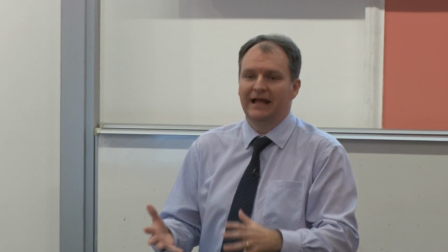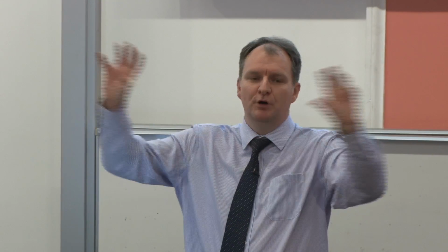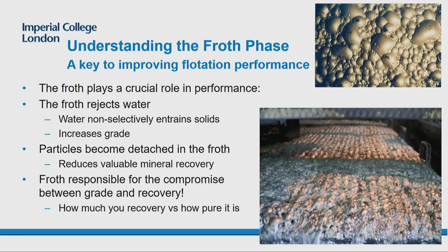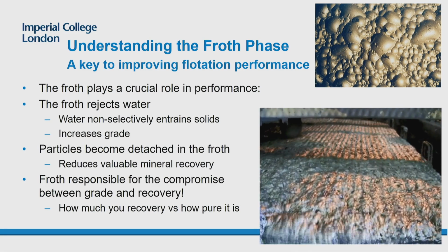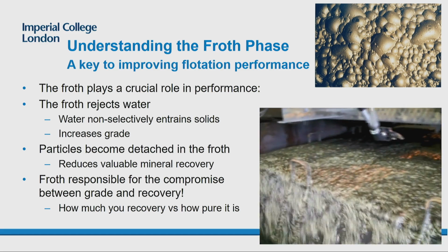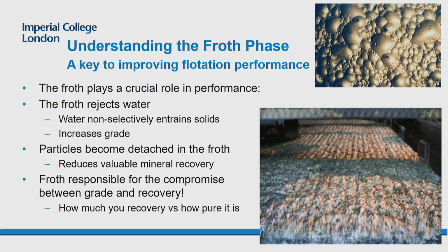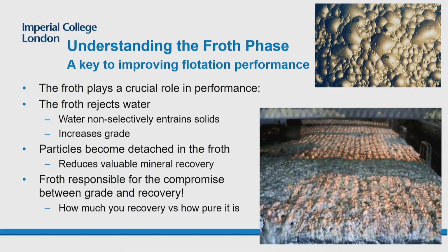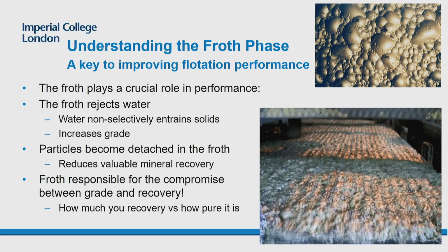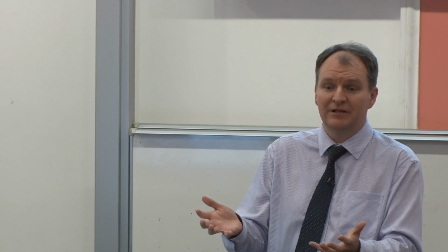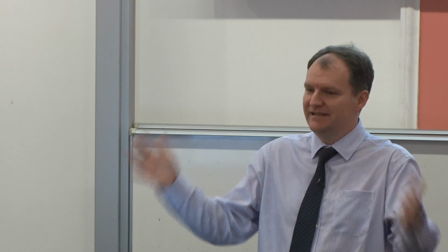If you've seen any froths, they get drier with height quite rapidly, and so you have a froth that is drier, and so you can pull over a drier froth and therefore pull over a purer product. And that is typically controlled, or it's indirectly controlled, by the size of the bubbles. The bigger the bubbles, the drier the froth, the lower the liquid content, and so the higher the grade you pull over. This, of course, also has the opposite effect on your recovery, because the particles you want are stuck to the surface of these bubbles, and so as your bubbles grow, you're losing surface area, and so you lose some of the stuff you actually want.